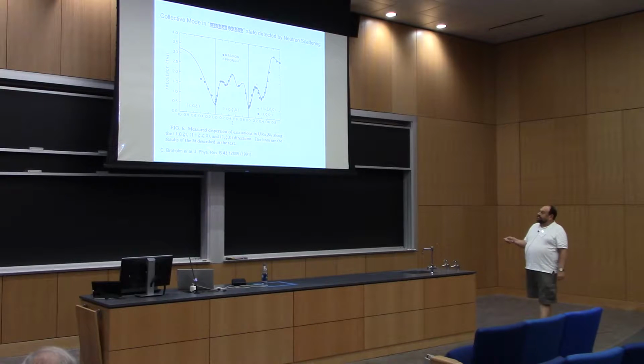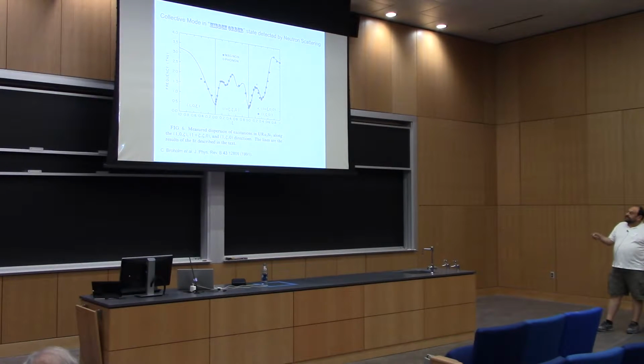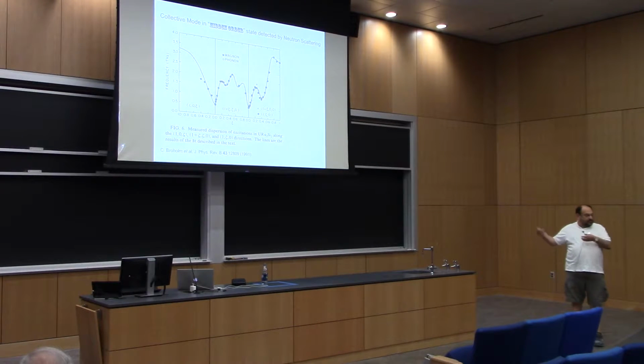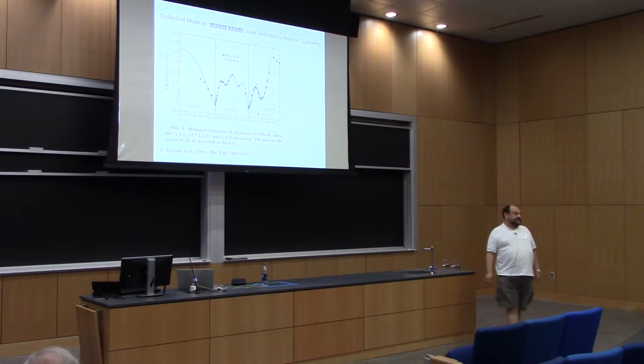They say it's essentially like this is the gap that was discussed this morning. Now, this is Broholm's thesis work, which goes back also 30 years, and already then he drew this dispersion of a collective mode. So there is a commensurate vector at 1, 0, 0. There is an excitation which is exactly the same energy as Sean showed now in Raman data. So we do know the symmetry of that excitation, which neutrons couldn't say, even though they already knew that it transforms as Jz. They see it in the longitudinal non-spin-flip channel. But entirely consistent now with the Raman work, which mainly couples to orbitals, we know that this excitation has an orbital A2g symmetry.